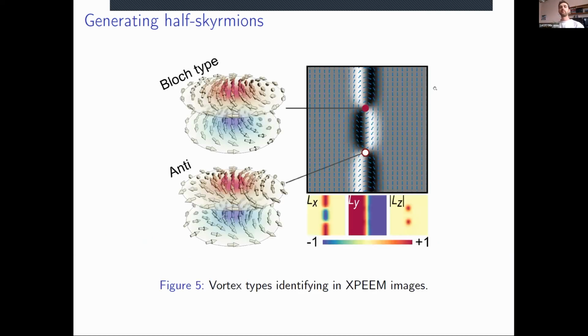So using micromagnetic simulations, just one example of this chirality reversal, the 2 pinch points either side, we identify as being these vortex structures. So you can see from the top sublattice spins that they swirl in a typical vortex-like structure around that pinch point. And the out-of-plane component we identify, so that's shown by LZ here, the magnitude of LZ.